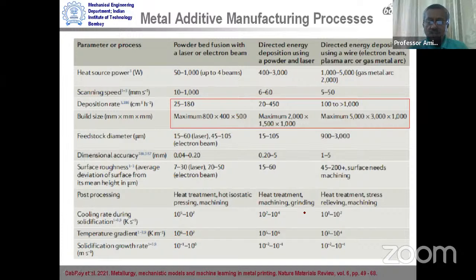Of course, there are other variables that are also very important to note. We will have a much higher cooling rate on a powder bed process because the melt pool is very small, and usually it happens at a much higher scanning speed, as you notice here. Compared to that, the cooling rate in the GMA process, this welding or deposition process, is much smaller because the pool sizes are bigger.